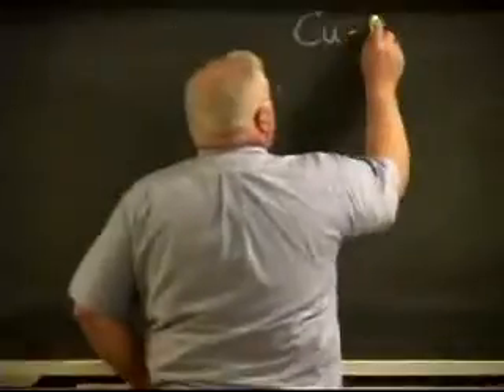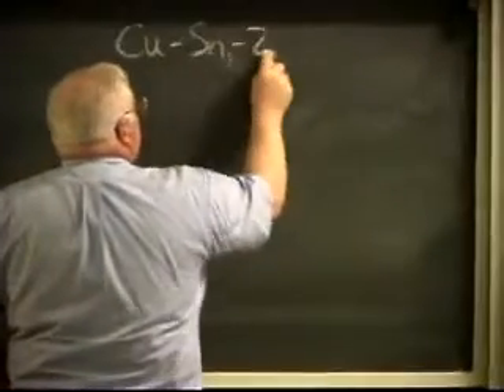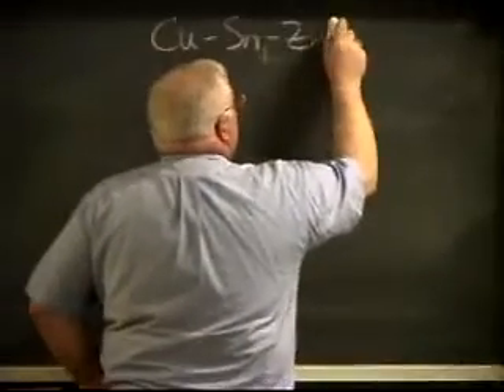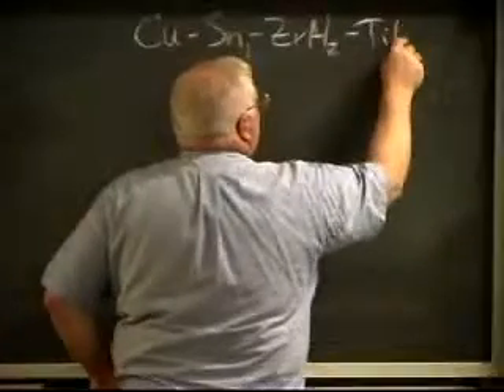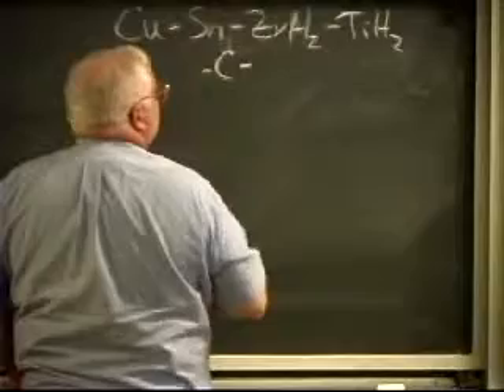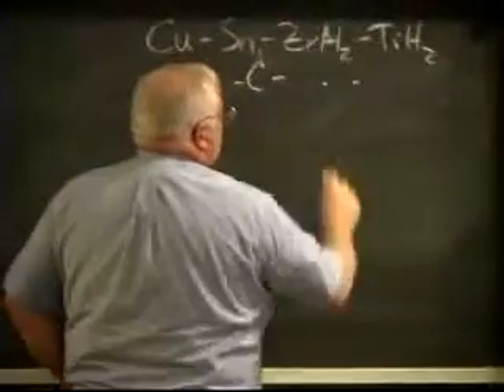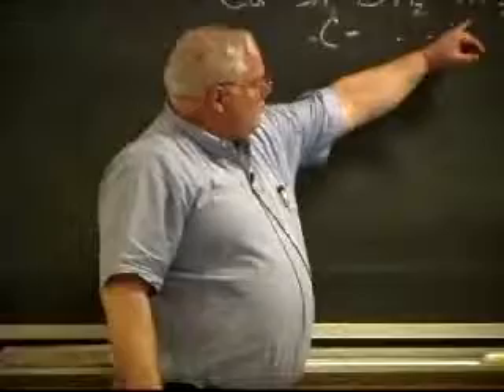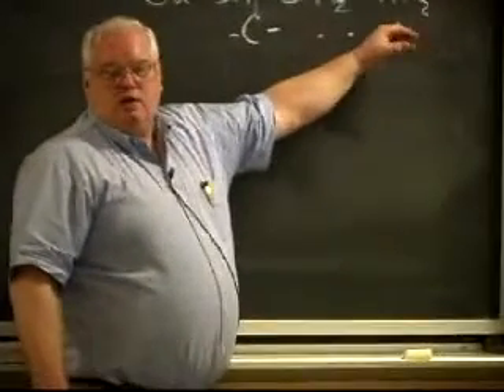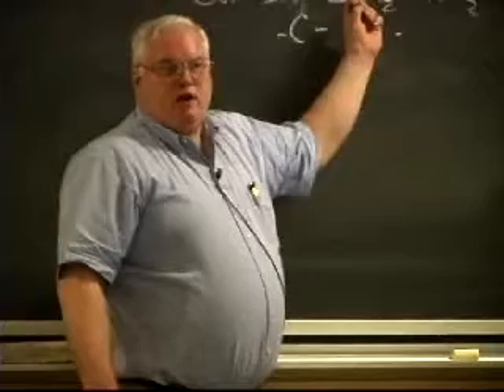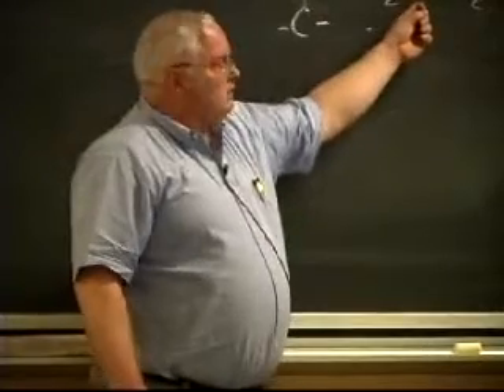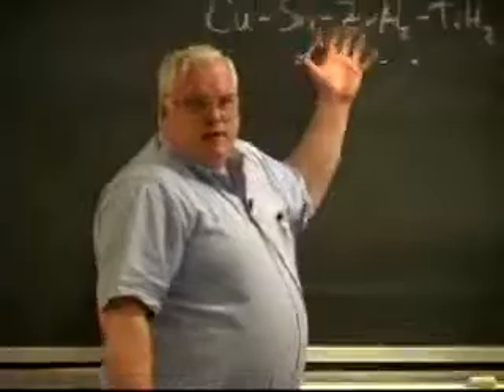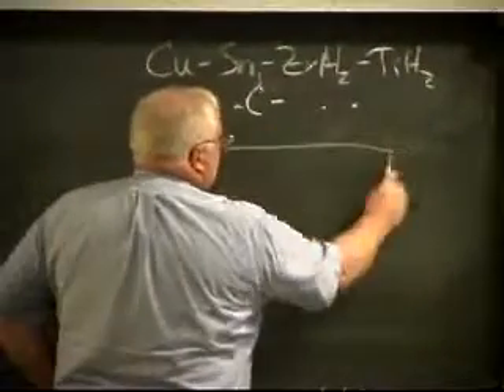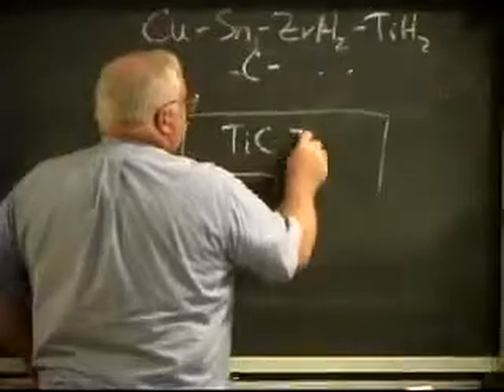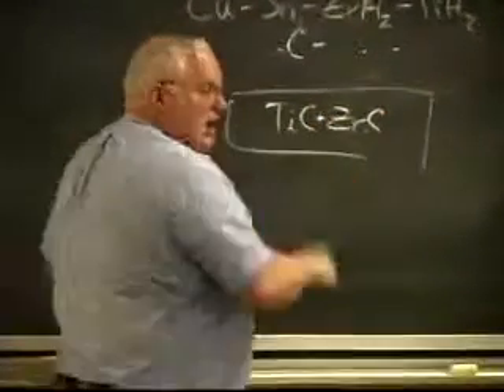It was a complex alloy. He would take copper powders and tin powders and zirconium powders, actually zirconium hydride powders, and titanium hydride powders, and carbon black soot, and there may have been a couple of other things in there. Basically what happens is the zirconium hydride and titanium hydride decompose as you heat them up. And so now you end up with pure zirconium metal and pure titanium metal. The copper tin was the basic matrix of the braze alloy, but we were really making a composite that had, when you're all done, titanium carbide and zirconium carbide. So it was half ceramic and half copper.